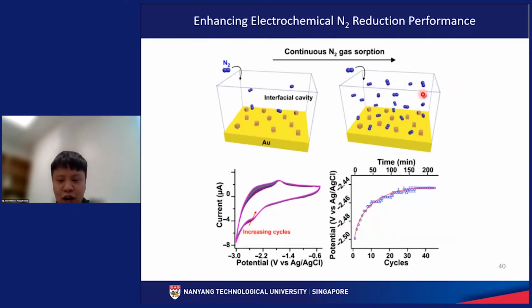Okay, we can also affirm that the interfacial cavity or the pseudo high pressure microenvironment can be used to enhance electrochemical nitrogen reduction performance. Over here, we hypothesize that nitrogen can be continuously accumulated in the interfacial cavity, and this will facilitate subsequent electrochemical reduction. From the cyclic voltammogram observed, we are able to note that the reduction potential of the cathodic peak will shift towards a more positive voltage. Shifting to a more positive voltage means that it is relatively easier for nitrogen reduction to take place. This is good because we want to reduce the overpotential that we use for our electrochemical reduction reaction.